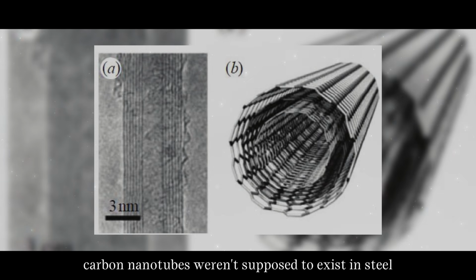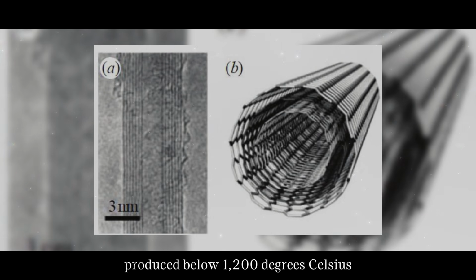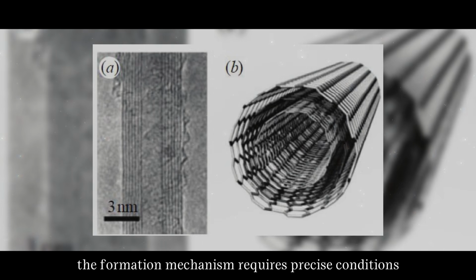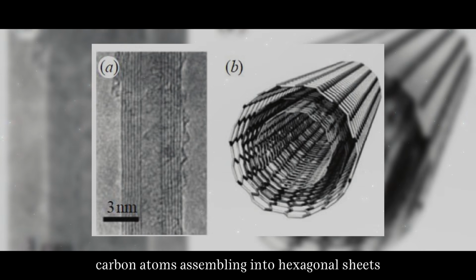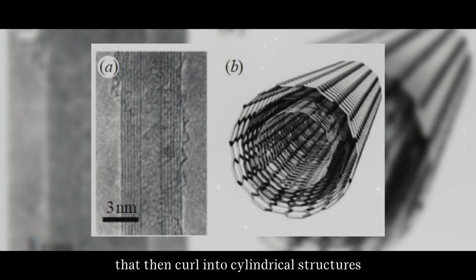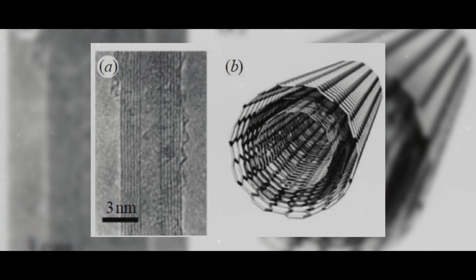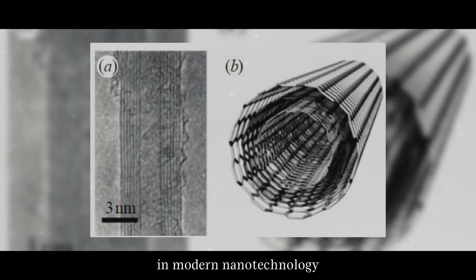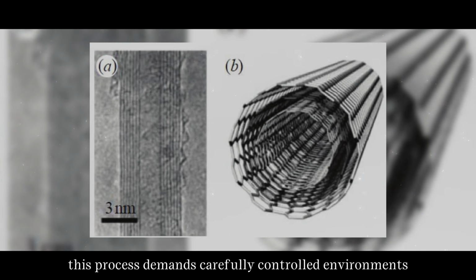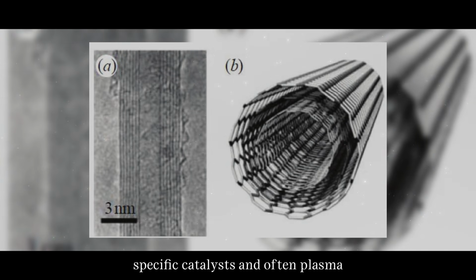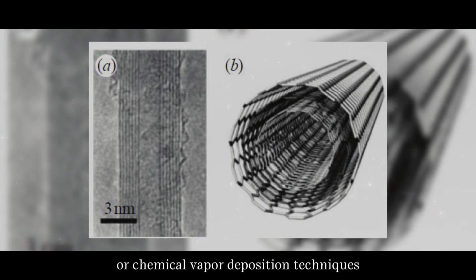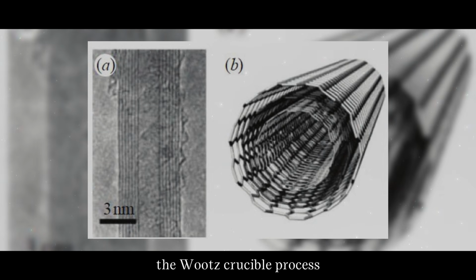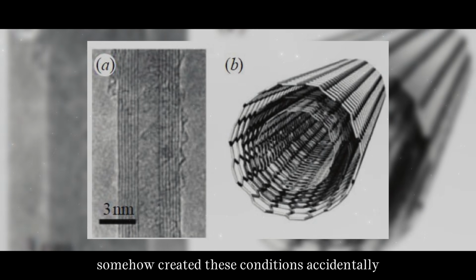Carbon nanotubes weren't supposed to exist in steel produced below 1,200 degrees Celsius. The formation mechanism requires precise conditions. Carbon atoms assembling into hexagonal sheets that then curl into cylindrical structures. In modern nanotechnology, this process demands carefully controlled environments, specific catalysts, and often plasma or chemical vapor deposition techniques. The wootz crucible process somehow created these conditions accidentally.